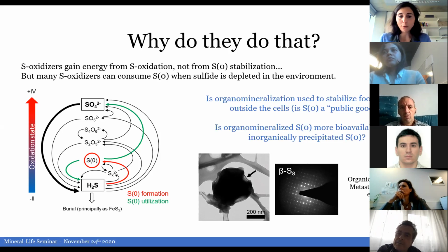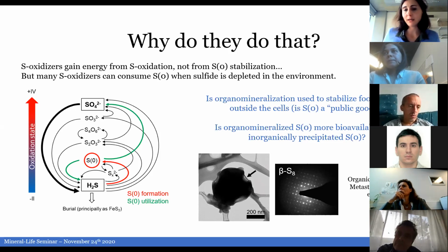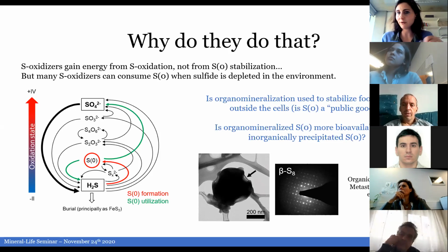No, what we know is that there seems to be something very specific in the way organics control the structure. At the beginning, I showed this experiment, which is just solution with organics and sulfide, and if you put glucose, you're going to get beta sulfur. If you put yeast extract, you're going to get beta and gamma. If you put glycine, you're going to get gamma sulfur.